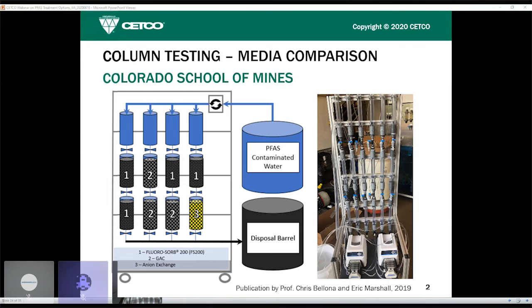So what this figure is showing is a system that was built at the Colorado School of Mines, where we had a segment and column system. We were comparing primarily GAC to FLUORO-SORB, as well as looking at FLUORO-SORB as a pretreatment to GAC and ion exchange. And for these experiments, we were shipped contaminated water from a site in the United States with relatively high PFAS levels. If you summed up the total of PFAS that were quantified in these samples, we were at around 60 to 80 micrograms per liter. Next slide.